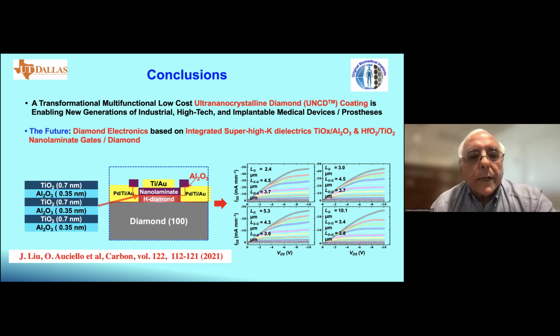And the future is that we demonstrated recently that we can grow high-K dielectric nanolaminates of titanium oxide and aluminum oxide on hydrogen-terminated diamond and produce the first CMOS devices based on diamond. And the reason we want to do it on diamond is because diamond is the highest thermal transport material, both perpendicular and in the surface. Graphene is higher in the surface, but perpendicular is too low. So single crystal diamond would be the way to really cool the next generation of microelectronic devices.